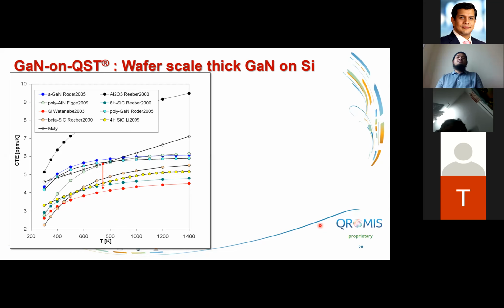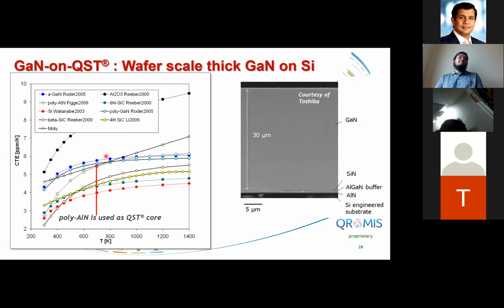So there is a company, Qromis, that came up with a proprietary technology where instead of directly making it on silicon, they make the substrate of polycrystalline aluminum nitride. And as we can see, the coefficient of thermal mismatch between polycrystalline aluminum nitride and gallium nitride is minimal, and their proprietary technology can enable very thick gallium nitride growth on silicon substrates.